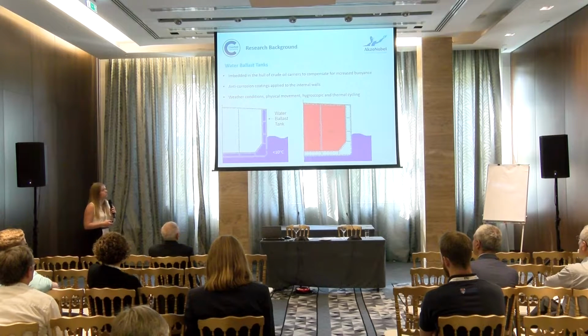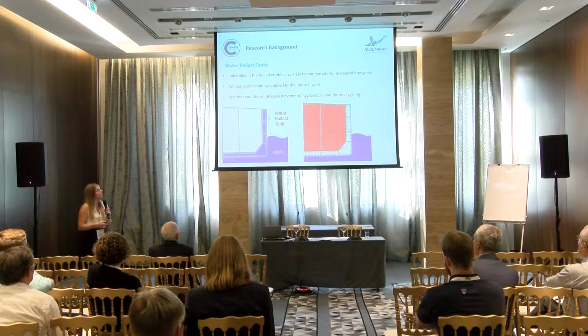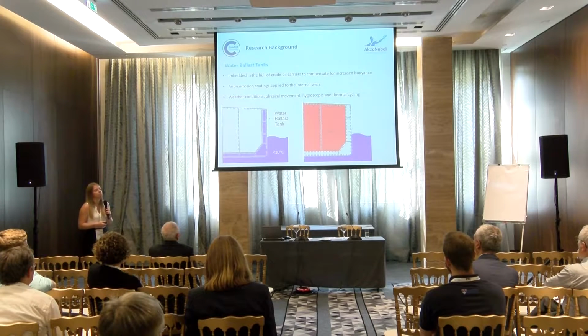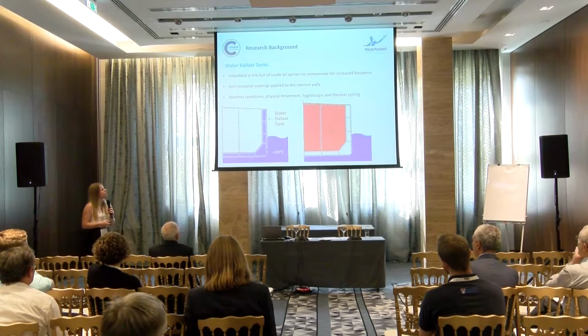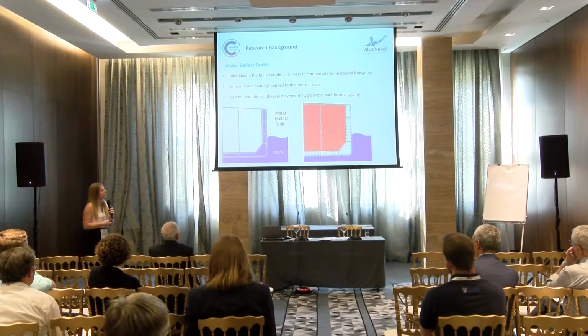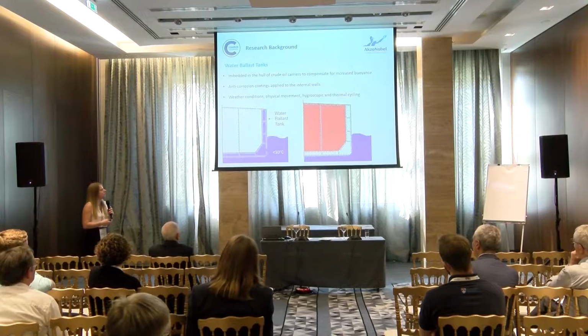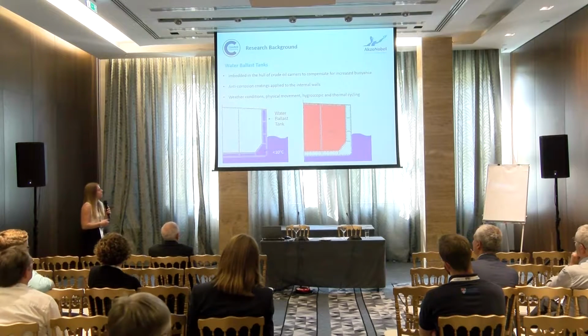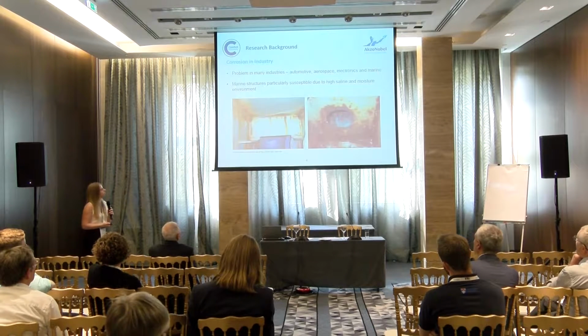Desorption and absorption of moisture will also result in coating shrinkage and swelling. And finally, there is a thermal fatigue cycle happening due to the crude oil, which is transported at approximately 60 degrees C, and seawater at less than 10 degrees C that is pumped in for ballast. And it is this temperature differential that my research is focusing on.